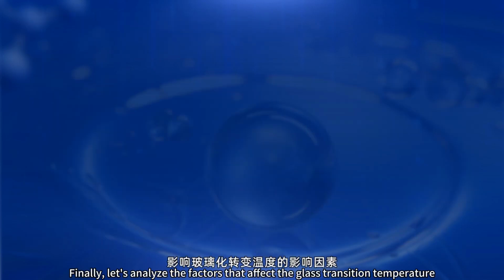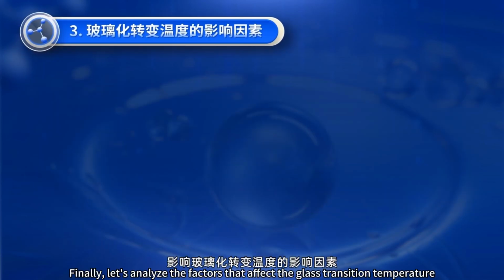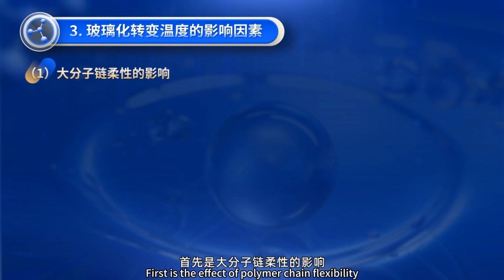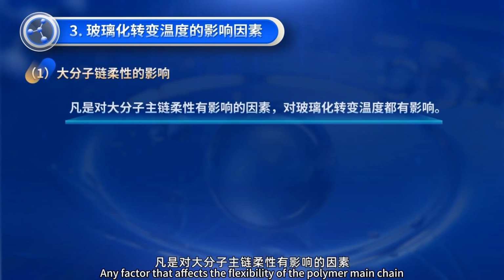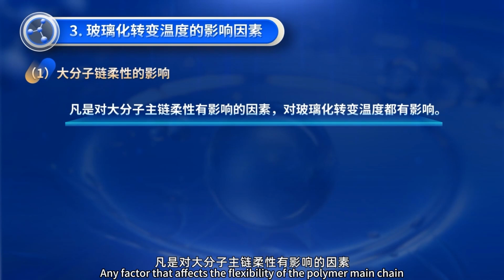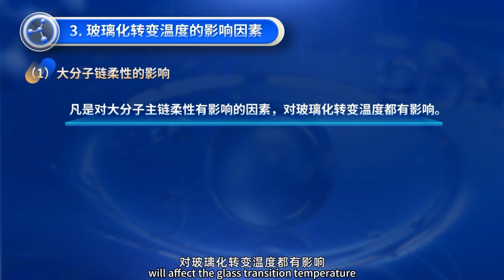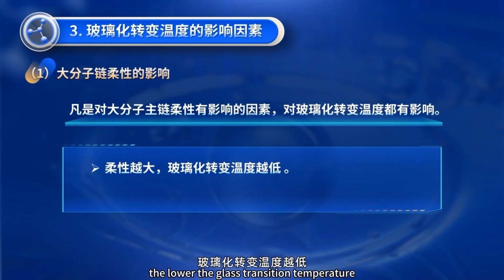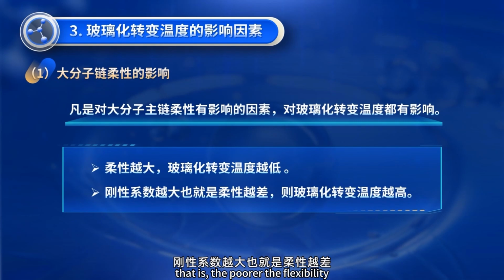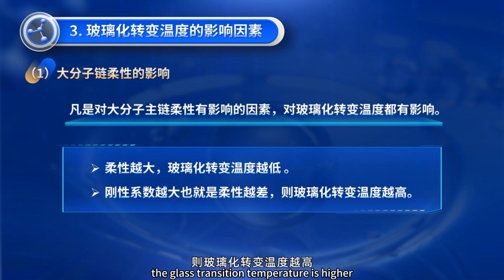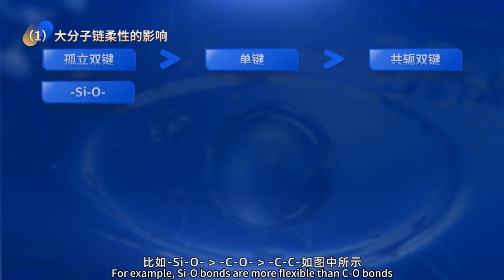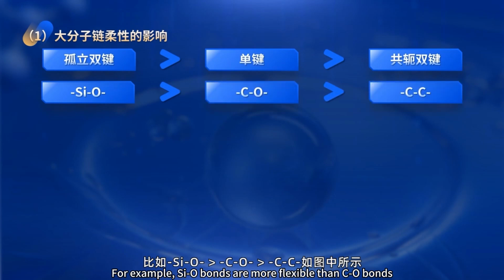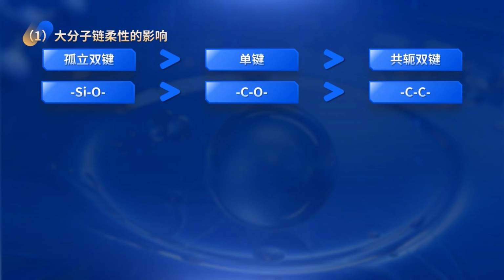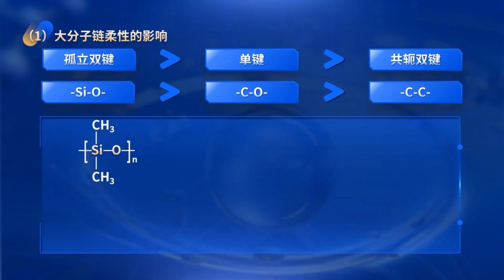Finally, let's analyze the factors that affect the glass transition temperature. First is the effect of polymer chain flexibility. Any factor that affects the flexibility of the polymer main chain will affect the glass transition temperature. The greater the flexibility, the lower the glass transition temperature. The higher the rigidity, that is, the poorer the flexibility, the higher the glass transition temperature. For example, Si-O bonds are more flexible than C-O bonds, which are more flexible than C-C bonds, as shown in the figure. Si-O bonds are the most flexible.